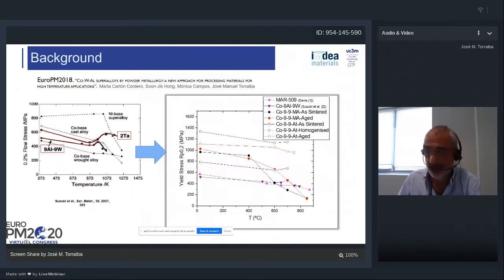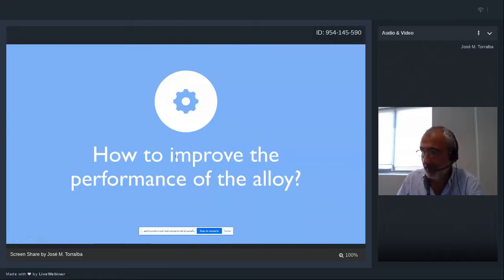These materials were compared with the materials also produced by mechanical alloying, and in this graph we can see in the bottom part the conventional nickel-based superalloys, and here the different alloys developed by us with tungsten and aluminum, in which we see that if we perform some heat treatments, we can improve the level of the yield stress at high temperature, even maintaining this high level at high temperature. We have to try to explain what happens, and we have to study how to improve the performance of these alloys.